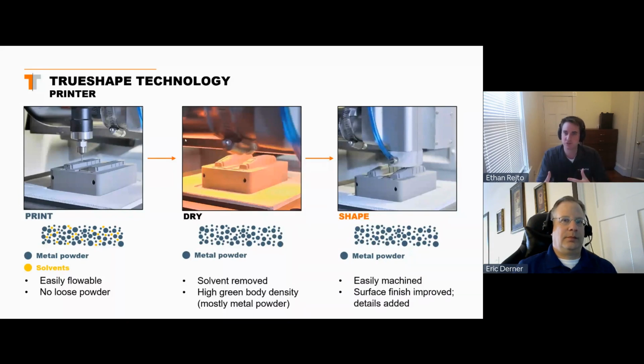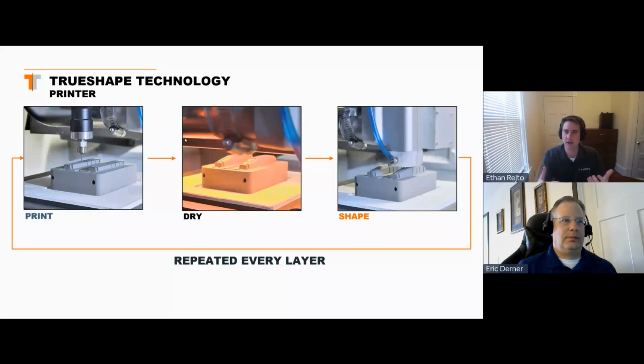So after we print and dry a layer, the part has roughly the consistency of a foam. We're going to come through and clean it up, and we're going to touch up the part. It's easy to machine. We're going to improve the surface finish. We're going to add any details that weren't possible to be printed, and we're going to remove some material there. So print, dry, shape, that's all happening every single layer, and this process is going to repeat to build up our part. At the end of the process, we're going to end up with what's called a green part.